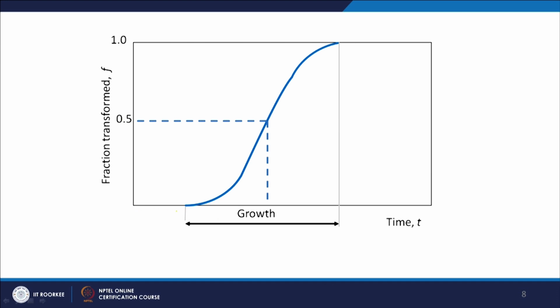There is some gap up to which time you will not have any transformation. You can understand this as a nucleation gap. Then it is slow, as we told you, then it accelerates. Then it goes into a steady state condition, and then it decelerates and becomes very slow at the end also. So, initially it is slow, and at the last stage also it is slow, and it has maximum growth kinetics in this central part. So, it is a typical S curve you will usually see in a lot of transformations, and you will see it in our phase transformation also. As a function of time, this shows the fraction transformed.